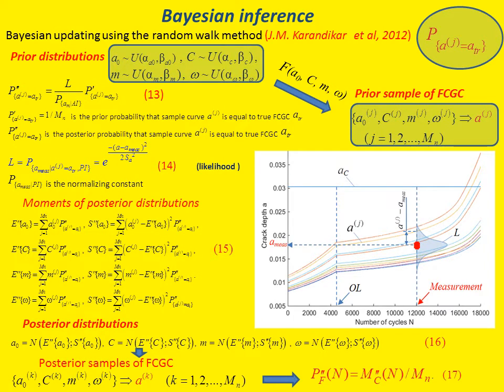As I have already mentioned, the damage parameters C, M, omega in equation 6' had been estimated during some laboratory tests, but they are not exactly relevant to the specific structural component. Due to the potential differences between the test and in-service conditions, there is a substantial uncertainty in these parameters. And subsequently, there is an uncertainty in crack size A. These uncertainties can be reduced by means of Bayesian inference that provides a rigorous mathematical framework of updating beliefs about uncertain parameters when the results of crack measurement became available.